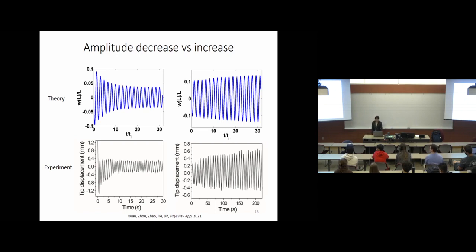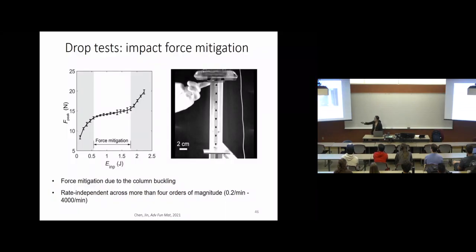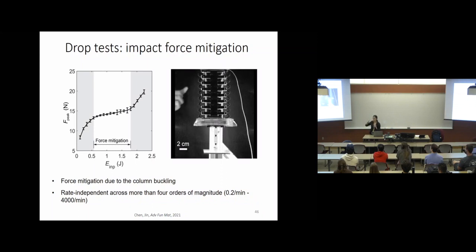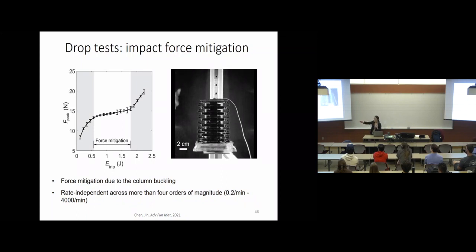Yes, yeah, we did this. Actually I didn't show you, but that's mainly in the second reference we listed there. Let me first show you this number. It's actually a little bit embarrassing. This number is fairly low. If you're familiar with this field, then this number, a few Joule, is relatively low. But to give you some sense, for a football helmet, typically you require 10 Joule for the energy absorption. And this we can't achieve with this material because we use a relatively soft material. If we increase the modulus, then we can achieve the energy required for a helmet, but it's very far away from a car collision.